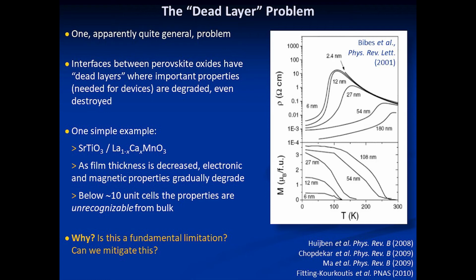And in one specific thing here, we took a specific kind of magnetic material, manganite, in our case it's a cobaltite. It's supposed to be magnetic and it's supposed to be metallic. And it turns out when you make it very thin, when you're very close to the substrate, to the interface with the other perovskite, its magnetic properties get worse and worse and worse, and eventually they completely disappear. And its conductivity gets worse and worse and worse, and eventually it completely disappears.